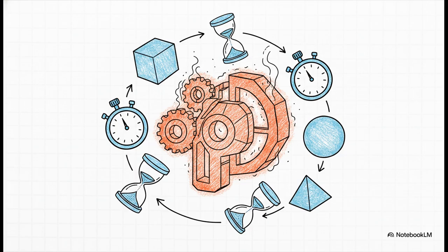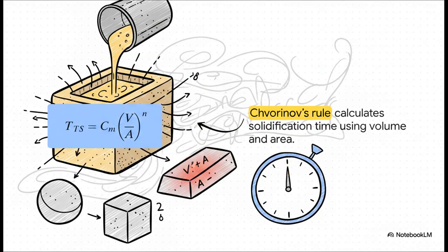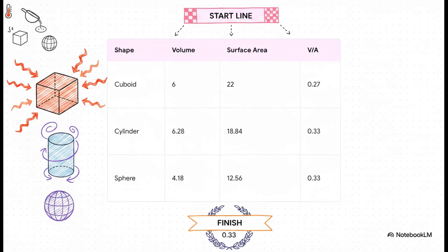The total time it takes for that liquid to turn completely solid strictly depends on the size and the shape of the casting. We can actually predict this down to the second using Chvorinov's rule. Now, while there's a constant in there for the mold material itself, the real star of the show is that fraction right in the parentheses, V over A, volume divided by surface area. Those two variables are the absolute key players dictating your countdown clock. Let's turn that math into a simple geometry race.